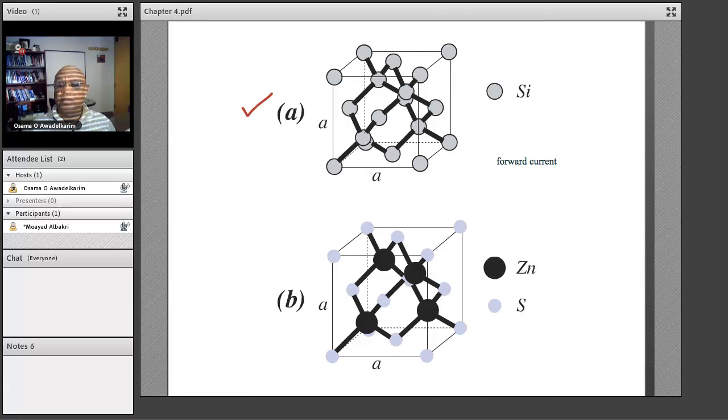Here is the diamond structure. You can see all the silicon atoms sitting in a cube, but you can see that this cube is much more complex than the simple cubic, the face-centered cubic, or the body-centered cubic. We have more atoms inside this cube and at the faces. And this comes from the 2 face-centered cubics that are displaced with respect to one another, and getting a cube out of it. One thing you see is that this atom here has 4 nearest neighbors.